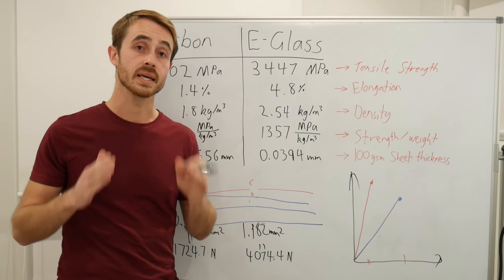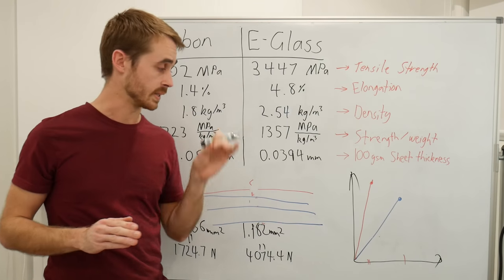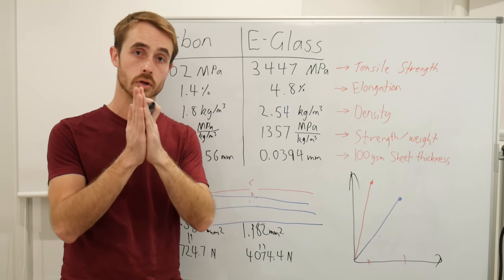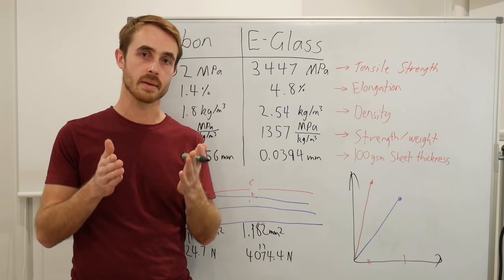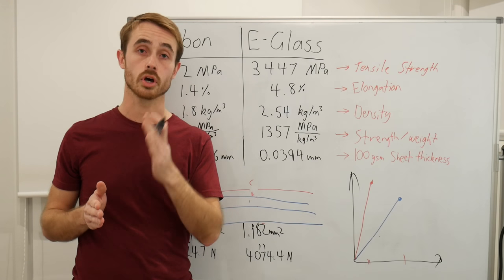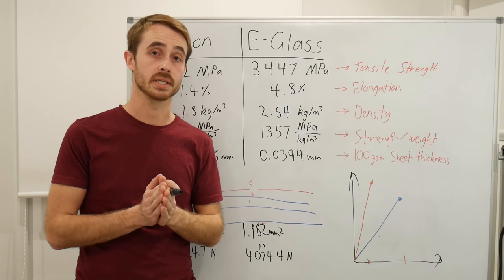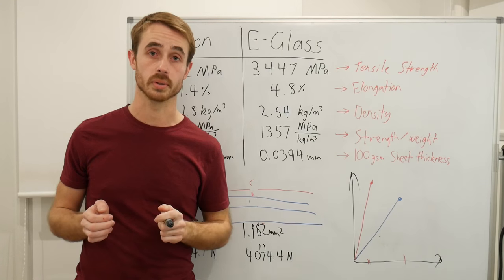If you're going to do composites properly, you've got to match your elongations correctly. There is no point laminating carbon fiber with fiberglass - you're better off matching it with something that's much closer on stiffness. There's a good reason at the amateur level to keep all your composites homogeneous, because then you know you have matched stiffness and you know what properties you're getting. Don't mix and match unless you really know what you're doing.